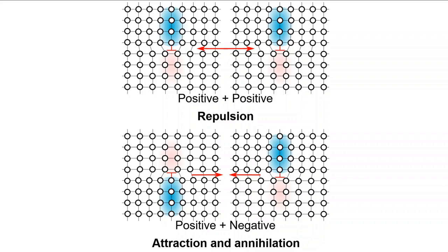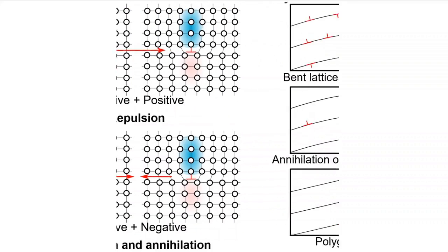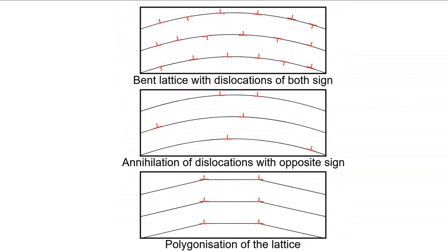We know that dislocations require shear applied to lattice to move. As temperature is increased, then there are unbalanced internal stresses that can cause this to happen. This is a topic that I will cover in a subsequent lecture. For now, just bear in mind that exposing a metal to an increase in temperature results in dislocation movement. Starting off with a lattice that has a mix of dislocations with both orientations, increasing temperature allows negative and positive dislocations to interact and cancel.